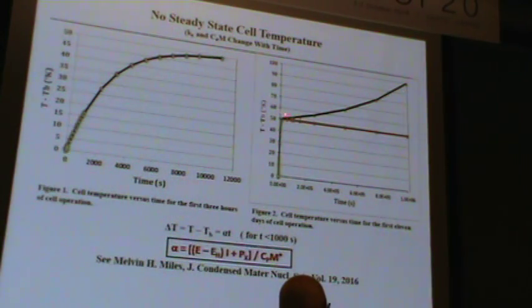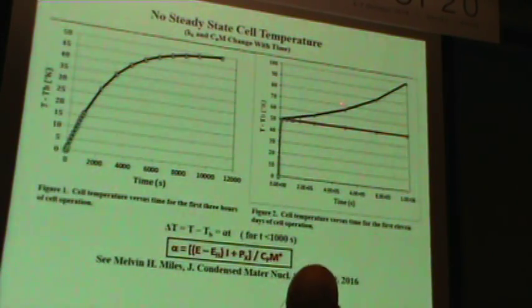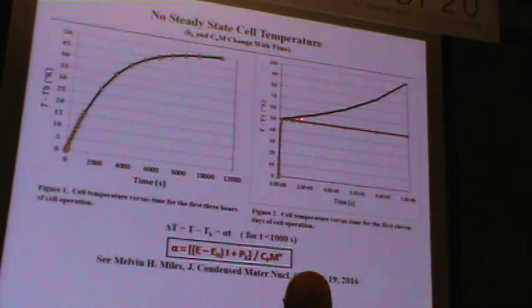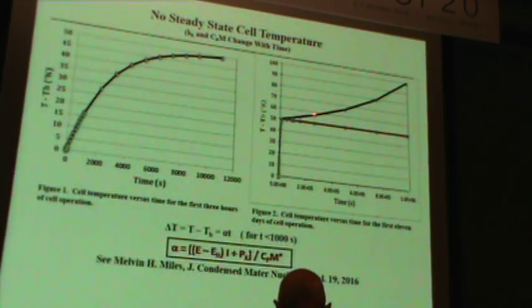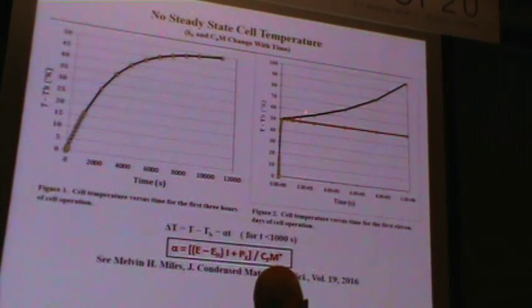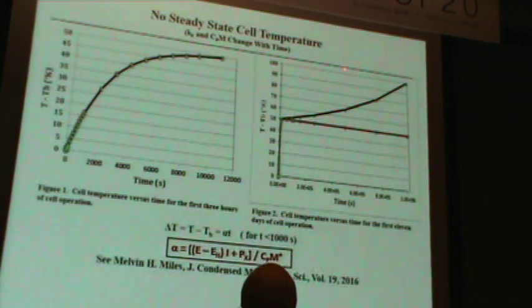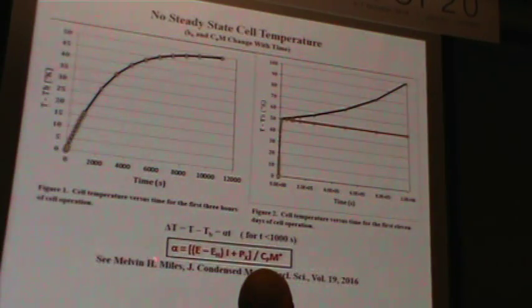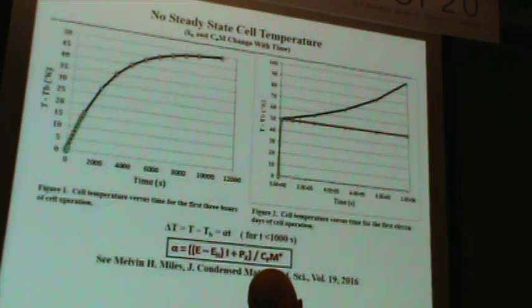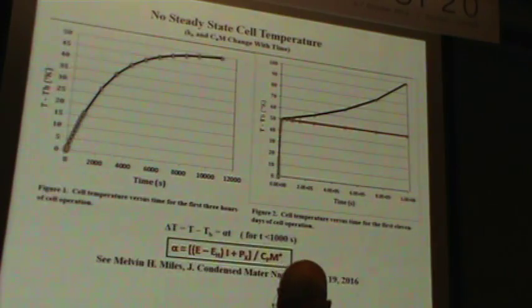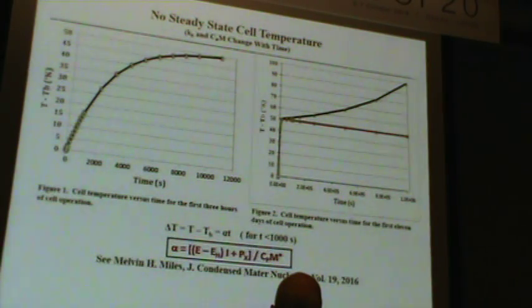Later on, if you make the simple assumptions, you get a constant temperature, but the actual behavior is that the cell temperature never reaches a steady state temperature. It keeps decreasing. Around here, you usually make up D2O, but you never reach a real steady state temperature. And it's linear in the early part, and the slope is given by this, so you can get some information out of that as well. If you start with the cell temperature and the bath temperature the same when you turn on the current, you can study the heating, how the cell heats, linearly at first.